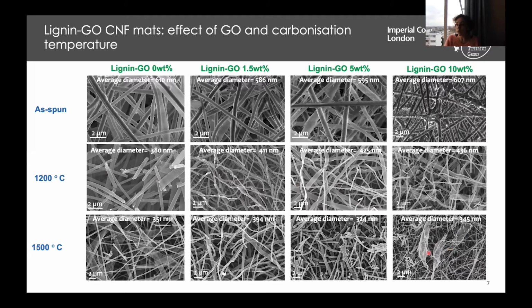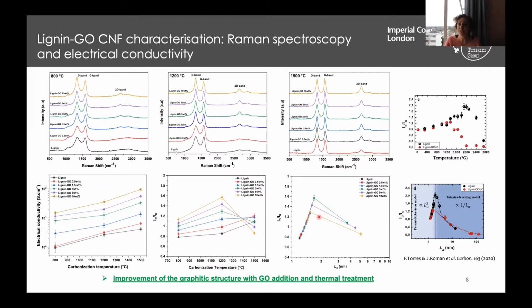Although when we go to very high graphene oxide contents, we can see that at the highest carbonization temperature, this graphene oxide tends to explode inside the fiber, as we can see here. And that is not very beneficial for our 3D freestanding mats. So we did some more characterization on Raman to see how this graphene oxide was helping the graphitization of our fibers. We can see for these different temperatures, 1200 degrees and 1500 degrees, how the ratio between the D and G band intensities changes with temperature and also with graphene oxide.